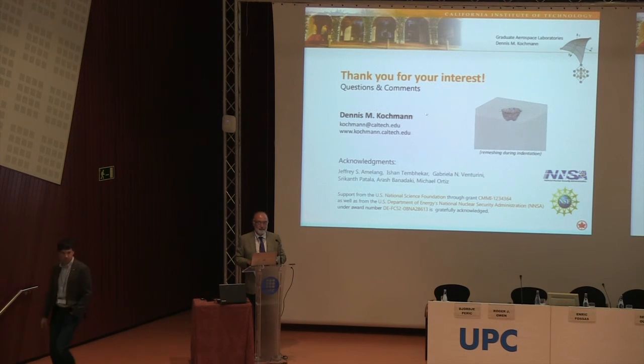Yes? Do you consider dislocation interactions with other dislocations? Oh, absolutely. So when you run atomistics, it's not discrete dislocation dynamics. So I don't even discretize a dislocation itself. If I run atomistics, I only consider the atomic motion. So if a dislocation comes moving in a particular direction, there are other dislocations around. They will naturally interact. They will certainly do, of course. That is accounted for.